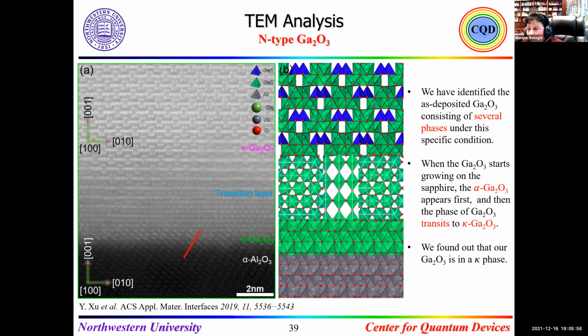Unfortunately, no, because local annealing requires a very special system in order to do it. We cannot, because we treat the whole crystal, the whole sample, which is about 1 square centimeter as an example. We do it in situ or ex situ under hydrogen, nitrogen, at the same time, so we don't do that - we cannot do the local annealing.